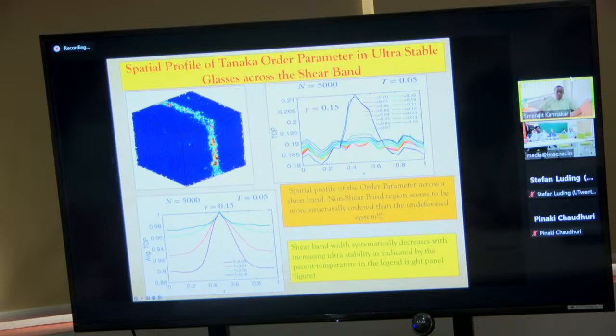because producing shear bands is now much easier for us than in a computer. And we also looked at what happens if you cool your sample at a different rate, which is defined by this parent temperature T. If you go to a very low temperature and then cool, versus if you take a high temperature liquid and cool, that will give you a different cooling rate in some sense. If you prepare your glass from a high temperature liquid, then you get a shear band which is much more diffuse. But if you get it in a well quenched glass, that will have a shear band which is significantly narrow.